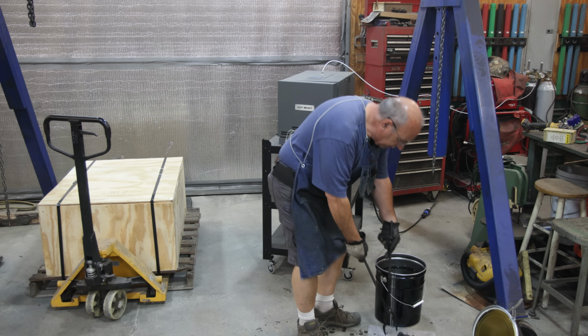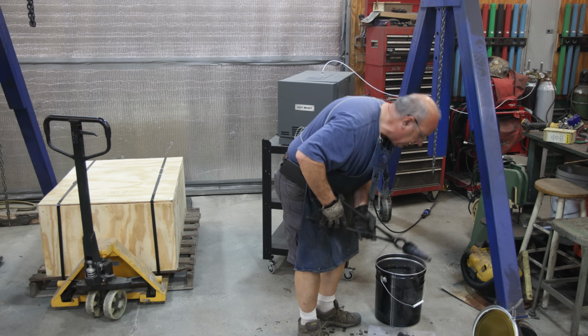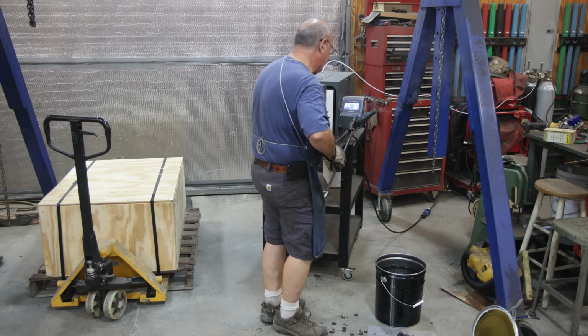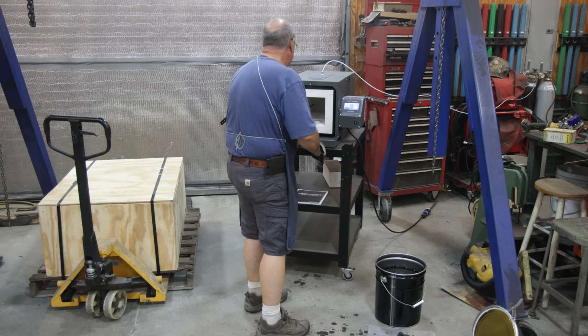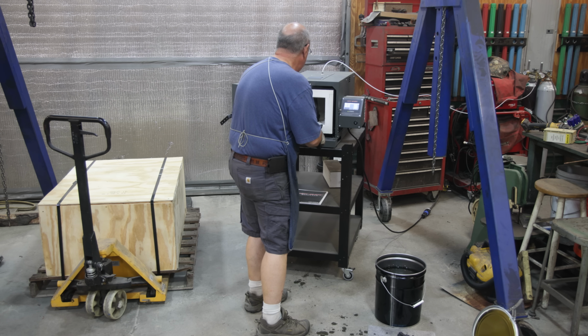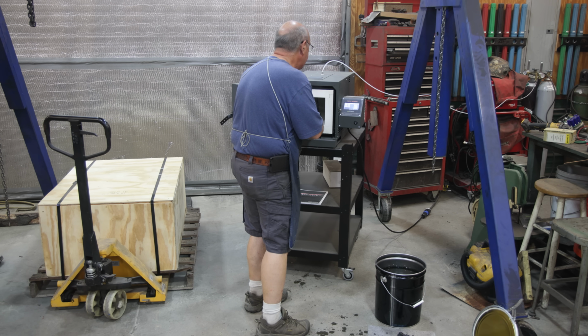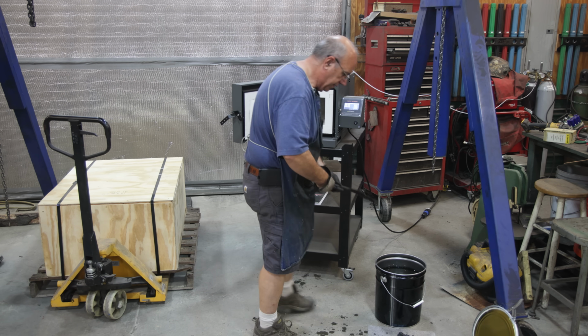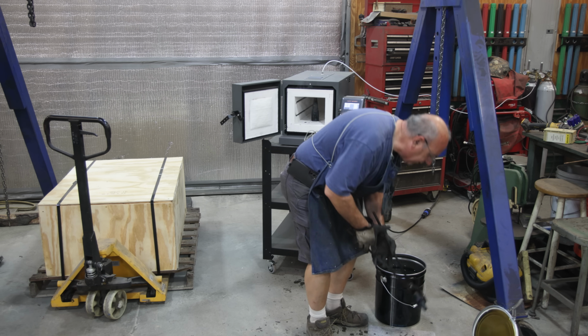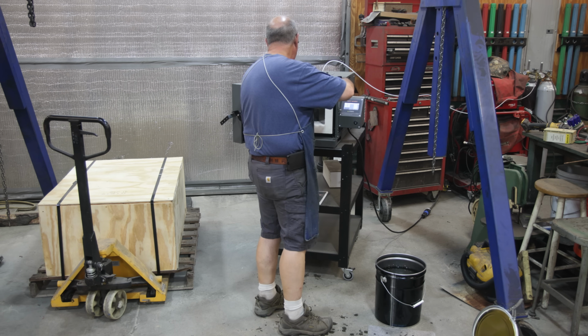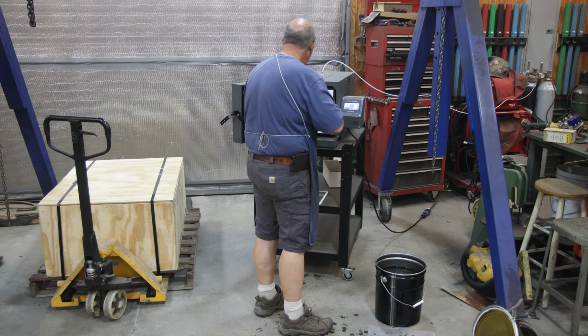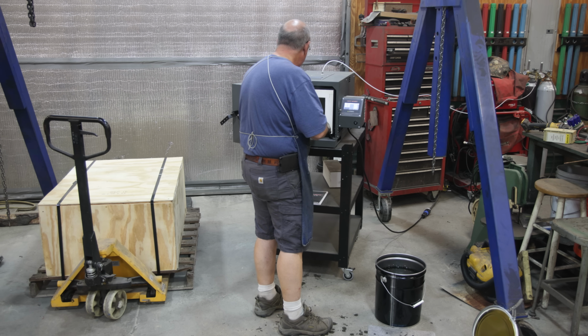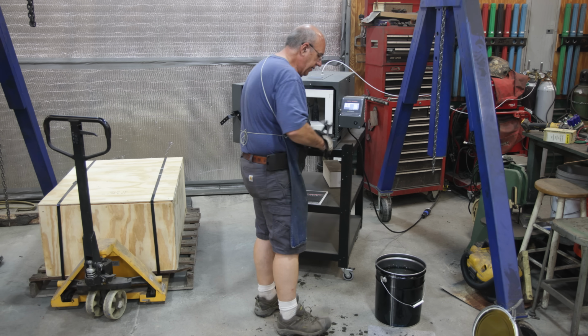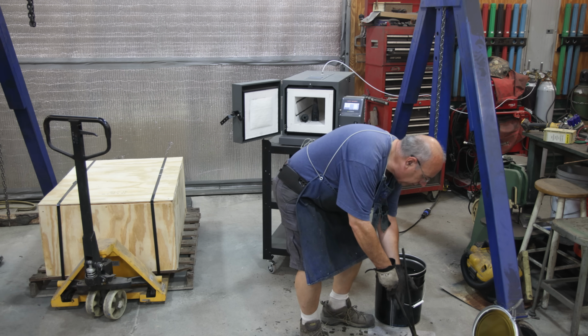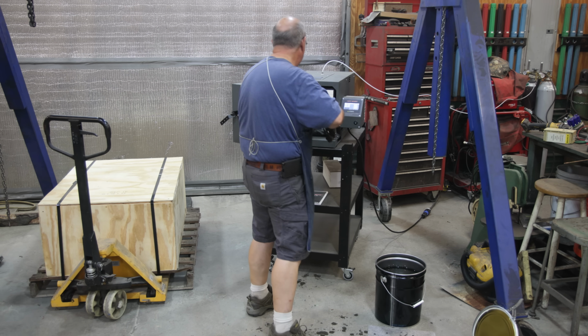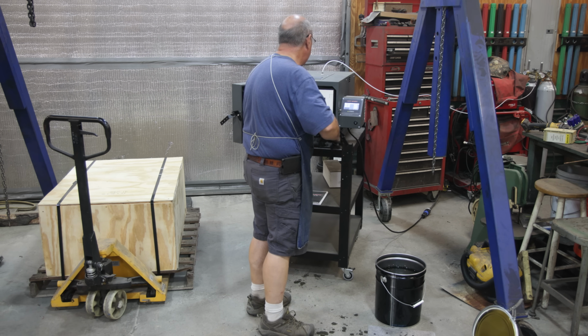So for the tempering, we're going to put the items back into the oven, and we want to be at about 800 degrees for this, and it needs to soak at 800 degrees for about 45 minutes, and then after that we can pull it out and just let it air cool. So I'm going to put the things back in the oven. I've got a program running.